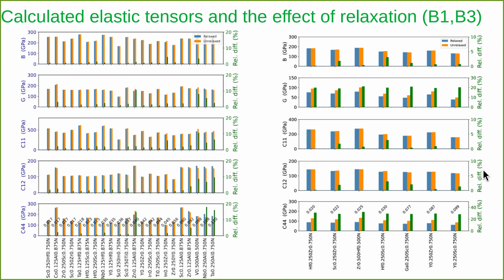So the difference is shown here in red on the right hand side. In some cases, in the shear modulus, it can go to 20% difference. So what we are saying at the end is that for the B1 structures, if you compare these numbers, the differences between the relaxed and unrelaxed elastic constants are small. So in the case of B1 structures, one can get a reasonably accurate database without atomic relaxation. Meanwhile, for B3, it is not the case. The error is much higher.